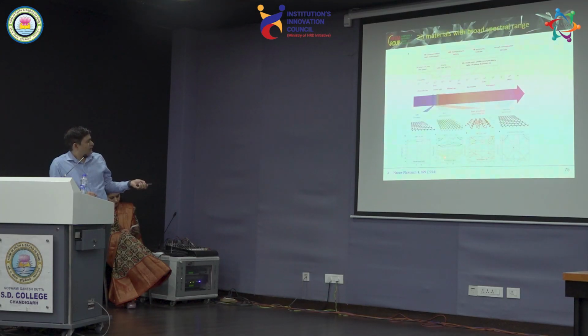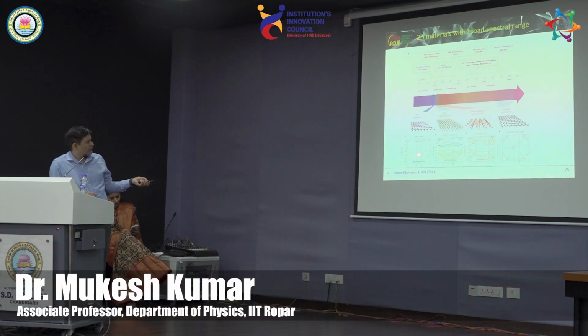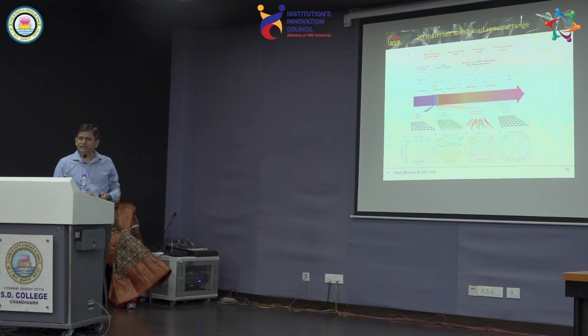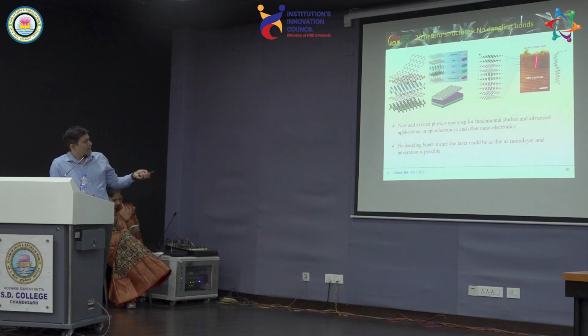Okay, so these have different band gaps, starting from graphene to hexagonal boron nitride. It's from 0 band gap all the way to 6 electron volt, and you can make their heterostructures. And the beauty is that they do not have any dangling bonds, so there is no problem of lattice mismatch. So they can go in any form, and then you can have different heterostructures of that.